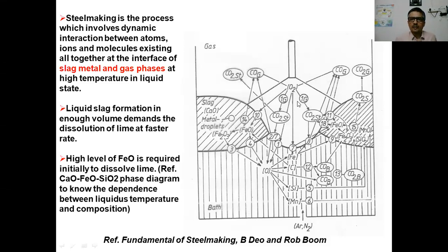In the middle part of the blow, you will find that the oxygen jet is striking, supplying the oxygen into the depth of the bath, and there are a lot of circulation streams, and on top of it there's a slag emulsion. There's a liquid slag, and except for carbon, all products of oxidation are liquid in nature. The product of oxidation of carbon is carbon monoxide. Those carbon monoxide gas bubbles are rising through the liquid slag on top of it, so it is forming the slag-metal emulsion. In addition to that, you may find a lot of floating undissolved lime particles as well.